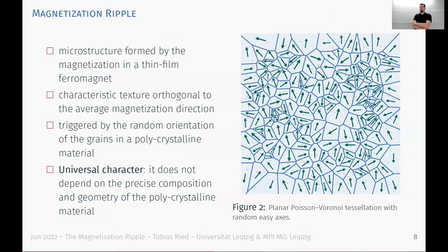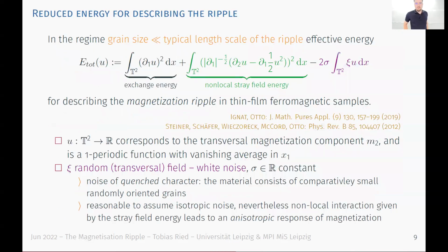Okay, but then this term in the overall function is not the leading order term in terms of derivatives. So you have the exchange energy, and in the Euler-Lagrange equation you should get a Laplacian from that. So exactly. Then what I didn't understand is why there's this strong singularity. It looks to me like we should have an equation with a deterministic Laplacian coming from the exchange energy, because that's always there, regardless of how the crystal is oriented, spins onto a line. So that's the exchange. And so the randomness is in a lower order term.